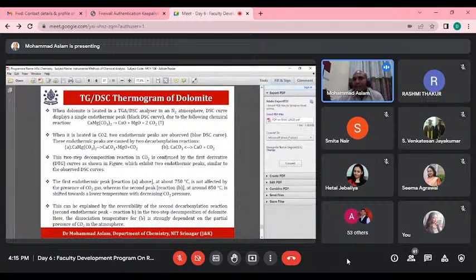Why is this reversible? Because here the CO2 partial pressure plays a very important role. Here the CaCO3 is basically calcite, a pure calcite. If your sample is contaminated with calcite, then these reactions will be larger, and the area under the DSC thermogram will be larger. On the basis of that, you can easily find out what type of contamination is there or not.